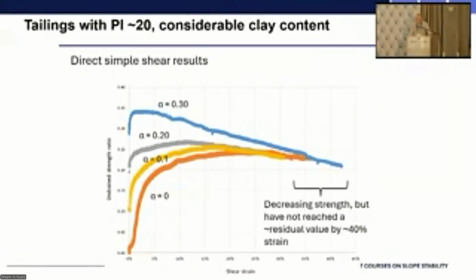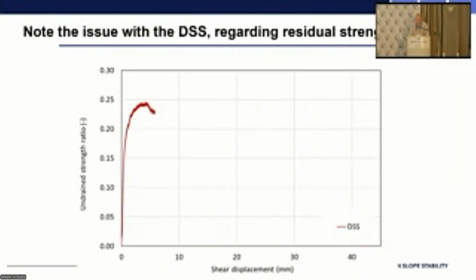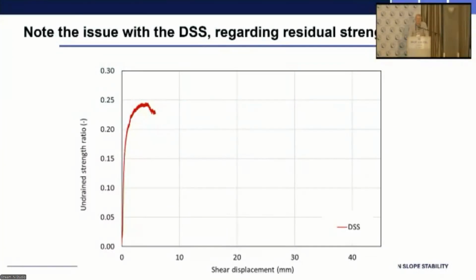And in this case, eventually they kind of converge perhaps on a large strain strength, but we still haven't stabilized. We still haven't got to a limiting condition in this case. Now, the DSS, we see that being used a lot for predicting large strain strengths. But the trouble is, you really don't mobilize a lot of displacement in the direct shear apparatus.